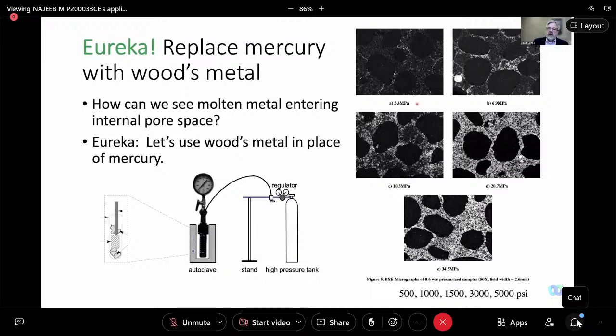A pressure of 3.4 megapascal, B 6.9 megapascal, and so forth. And we then could slice these samples and use a scanning electron microscope to visualize where did the mercury go, or in this case, Wood's metal go in this microstructure. And you can see that by the time we get to 34,000, for 34 megapascal, we've got a fairly complete, widespread intrusion of the Wood's metal into the microstructure, and that helps us understand what was happening in the MIP experiments,